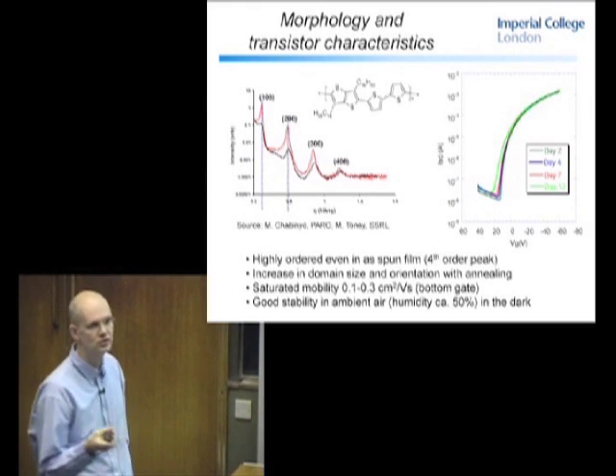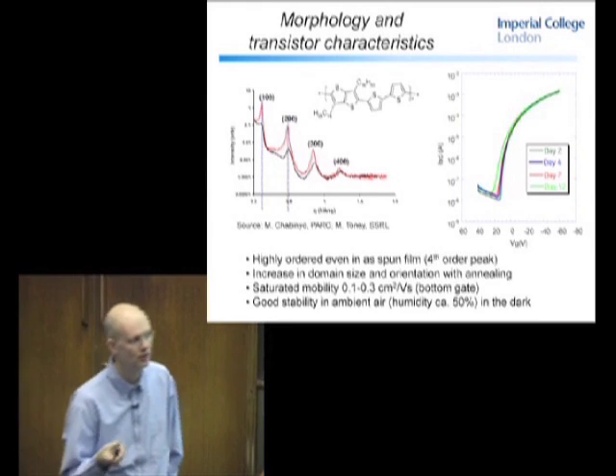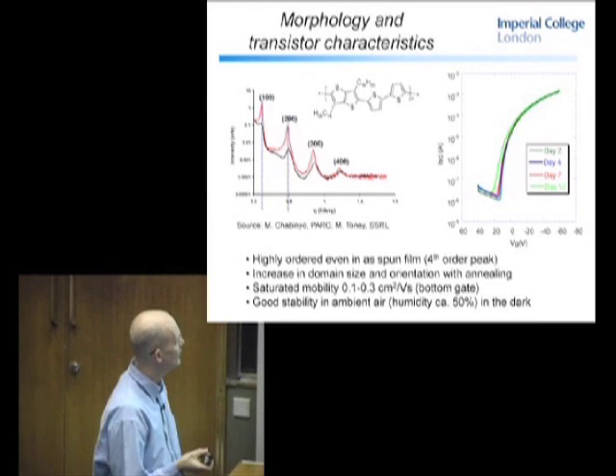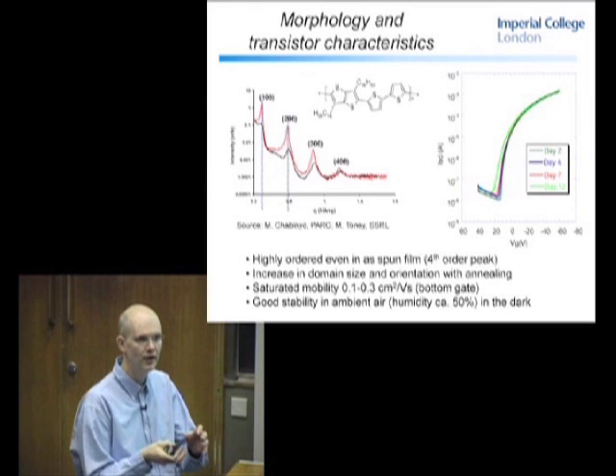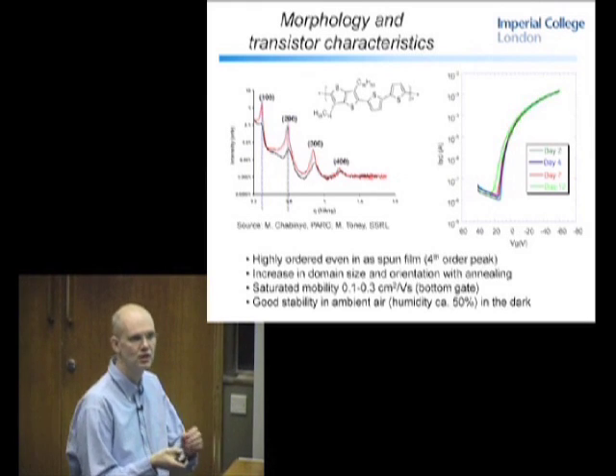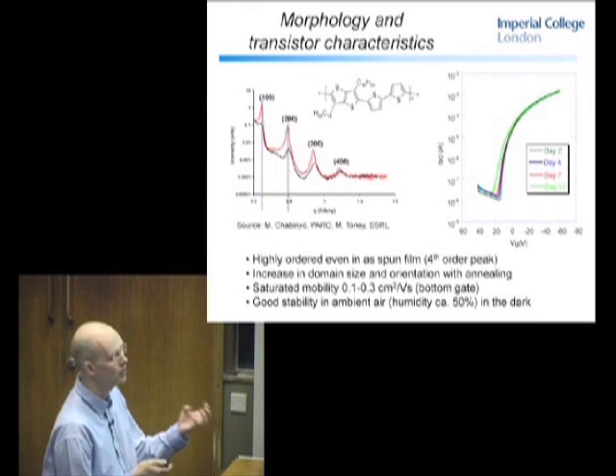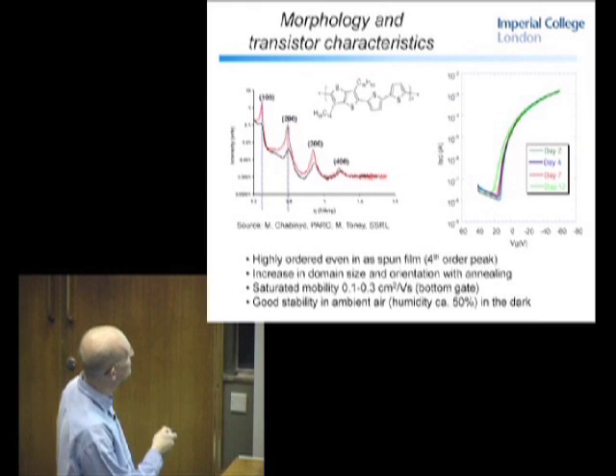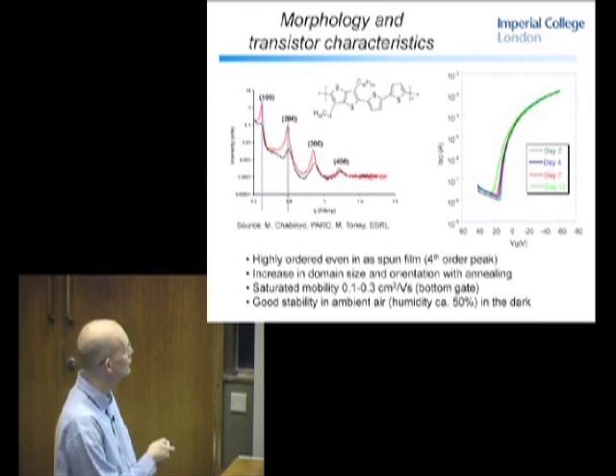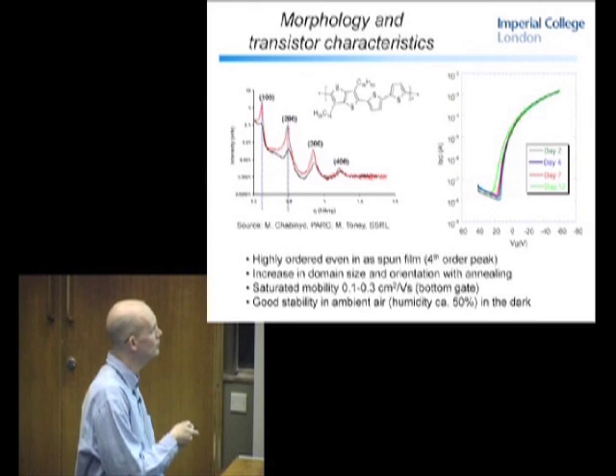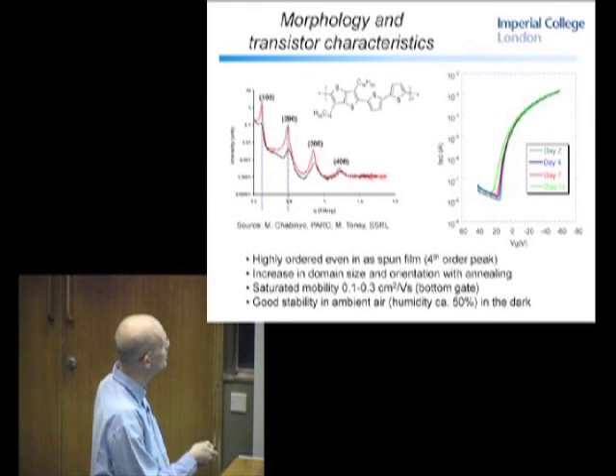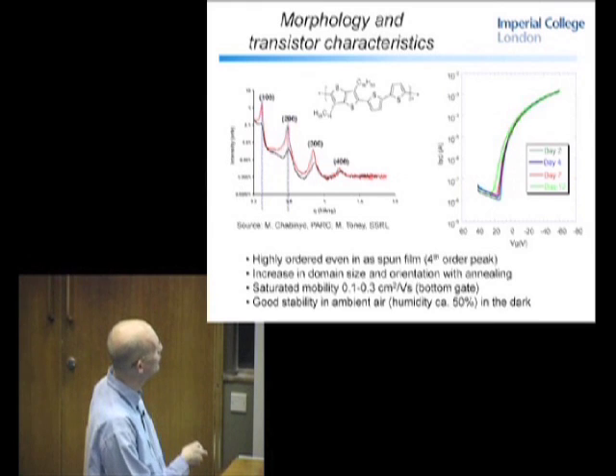So if you look at these semiconductor materials, as I mentioned earlier, they're not that soluble. But in fact, what you're forming could be little microaggregates, almost like nano dispersions, and when you spin them, you've already got structural order. And it seems to be the case here anyway. There's no annealing required. You just drive off the solvent, or you can blow it off at ambient conditions, and you get highly ordered, good mobility materials.